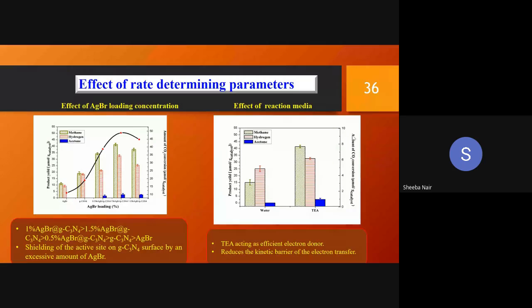So these were the results of that AgBr composite. You can see that 1% composite of AgBr and graphitic nitride had given us the better results when compared to others. Whereas 1.5% also was a little closer to 1%, but we took 1% as the optimum because making 1.5% AgBr is again an additional economical impact on the industry. So we stopped with the 1% AgBr.